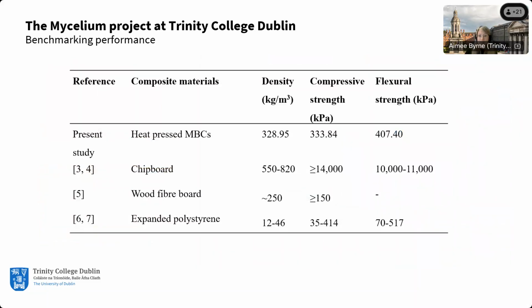So we always like to then go back and see what application can we use this in. So we looked at some benchmark materials that might be comparable, and we found that looking at our maximum compression strength and flexural strength that we're able to attain, they're closest to the high end of expanded polystyrene. So those hard insulation boards that you might find off the shelf, something similar to the hardest of those or the most rigid of those that you might identify. That's as close as we're getting.